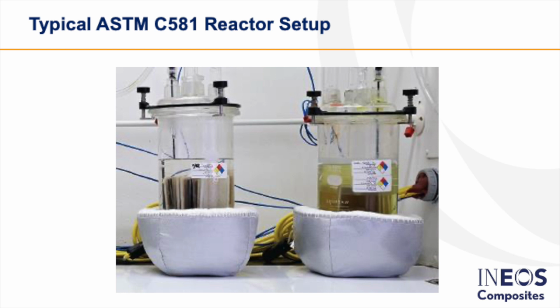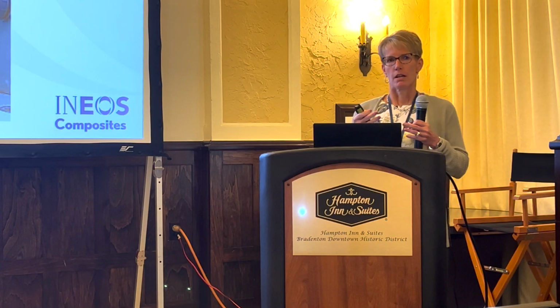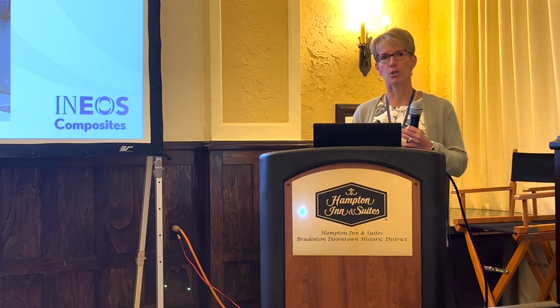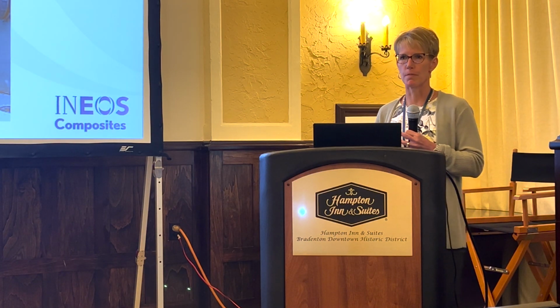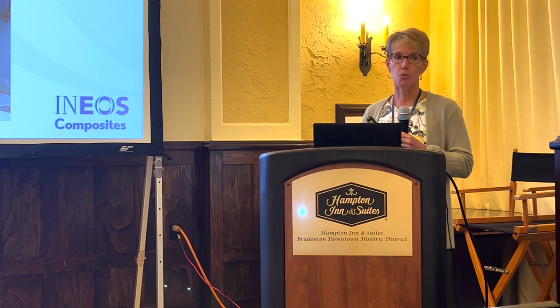This is a picture of what it would actually look like in the laboratory where we would test the coupons. We are able to immerse them in various chemicals. We can control the temperature and test them at elevated temperatures when necessary. And what we would normally do is immerse the coupons and then pull out a coupon at 1 month, 3 months, 6 months, and then 12 months.